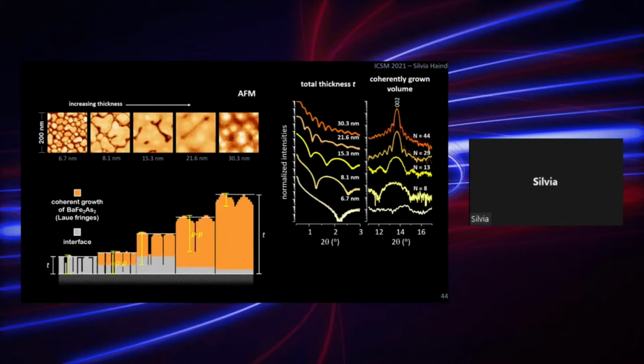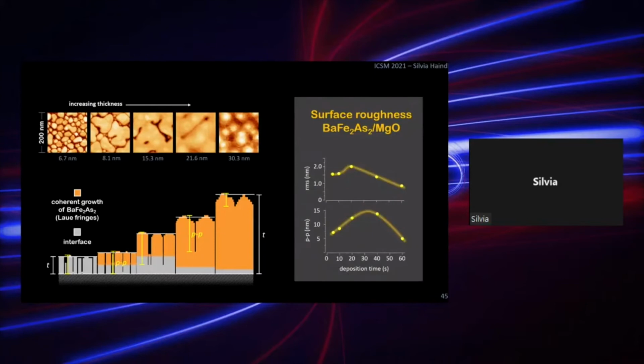So this is this gray section at the interface, and this can shrink if you grow the films thicker and thicker. Finally, you see also that in the very thin film limit, in that configuration here, the surface roughness is mainly determined by the peak-to-peak roughness of the islands. And only after you reach a threshold thickness of 30 nanometer will the roughness of the film be close to the RMS roughness due to this mound formation.